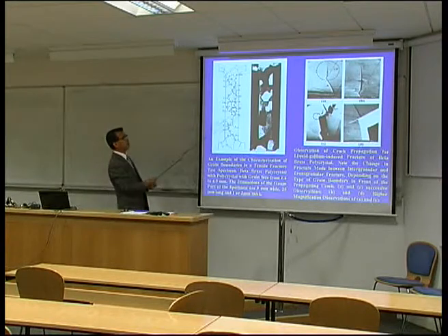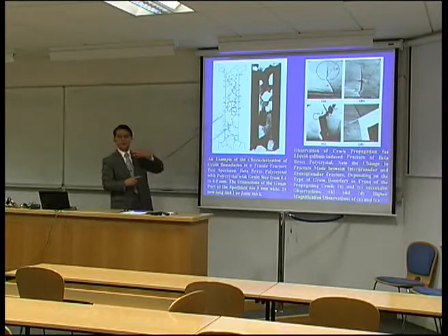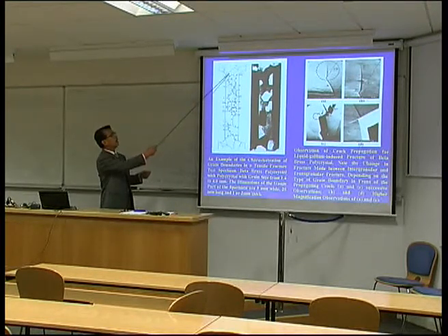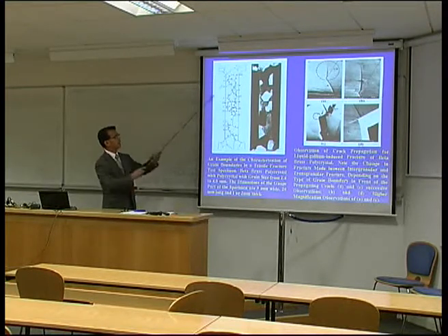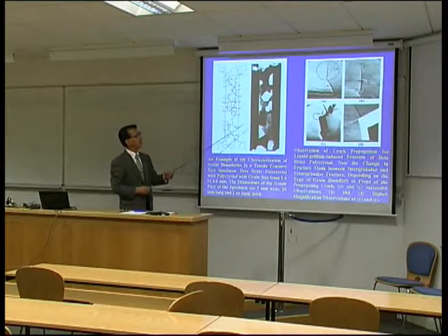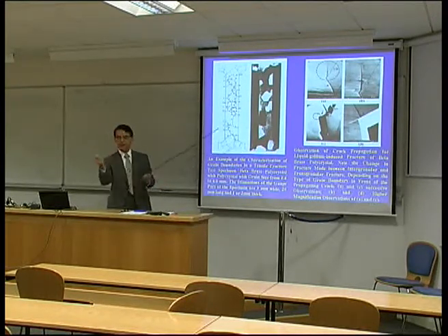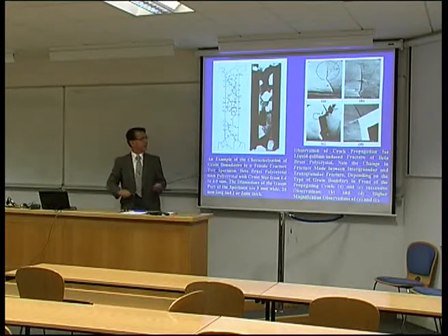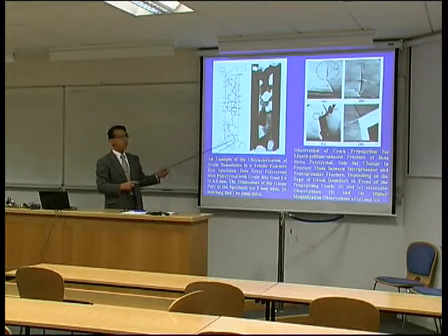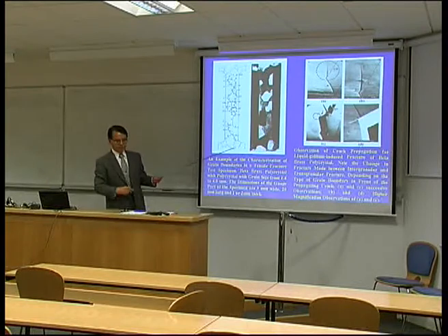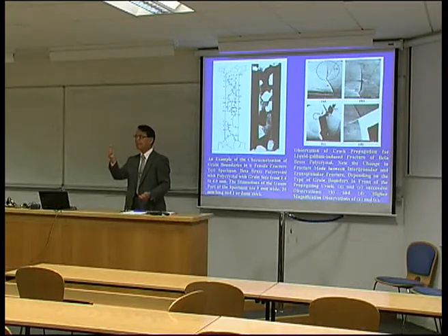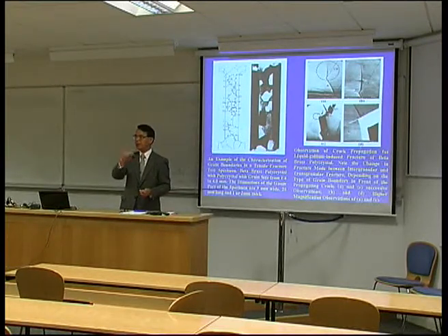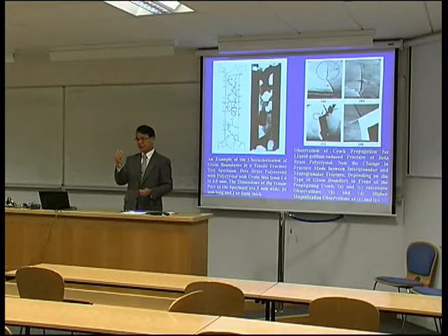About nearly 20 years ago, we made an in-situ observation of the fracture process in polycrystalline material. Before the fracture test, we characterized the whole grain bundle. And then, in this case, we put in gallium, just a bit, for liquid metal embrittlement. In this case, a copper, brass polycrystalline material, I think, can be very embrittled by gallium. But normally, without the wetting of gallium, it never fractures intergranularly, never.